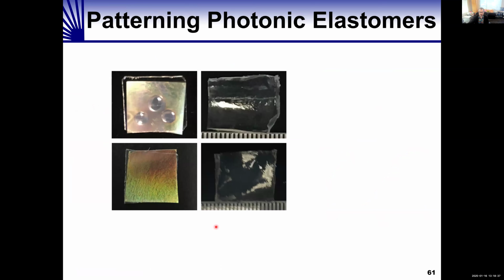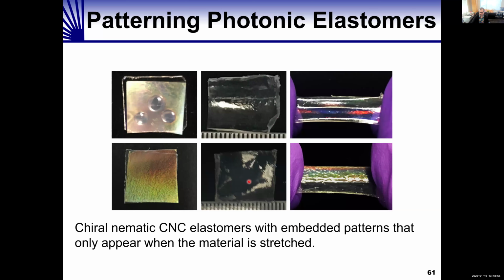We can also pattern our films by adding droplets of water, and that changes the helical pitch where the water's been added. So we made patterned films with the elastomer, and they are colorless and transparent. But when you stretch them, then you can see a pattern emerge.